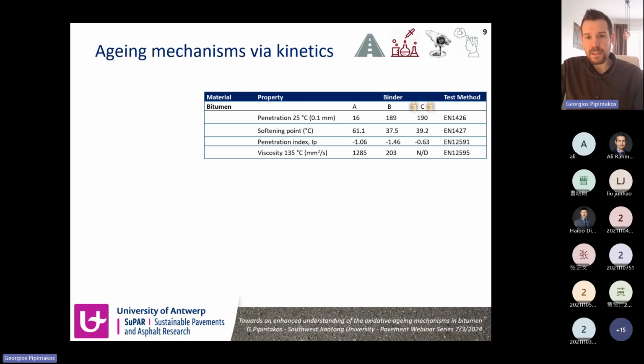So A and B were straight run binders. The difference with binder C was that binder C was the result of a visbreaking process, so the distillation process was different, and also it included waxes, paraffinic waxes, in its composition, as was checked by differential scanning calorimetry. And also this bitumen C had similar empirical performance properties with binder B.